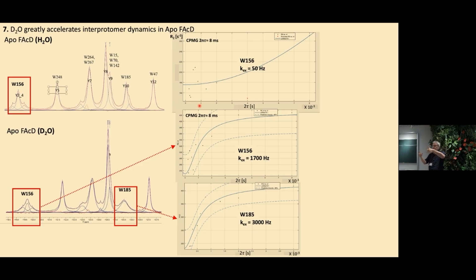All right, so the dynamic model here would be this enzyme interconverting between its ground and its excited state. And so what I'm trying to show you in this data is that in water, in the absence of a substrate, we can barely make out any kind of dynamics. There's just a lot of noise, and it's very difficult to measure this transition. However, as soon as we go from H2O to D2O, suddenly those dynamics sharpen up, and we can measure this process to be taking place on the order of 2,000 times per second. Right? Bang, snap, put in D2O, you have this reinforced dynamic transition between these two states.